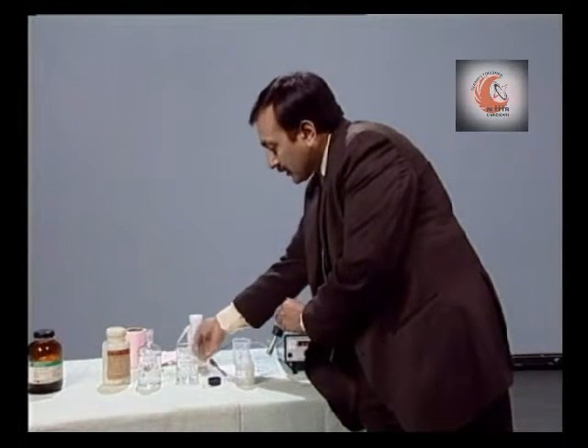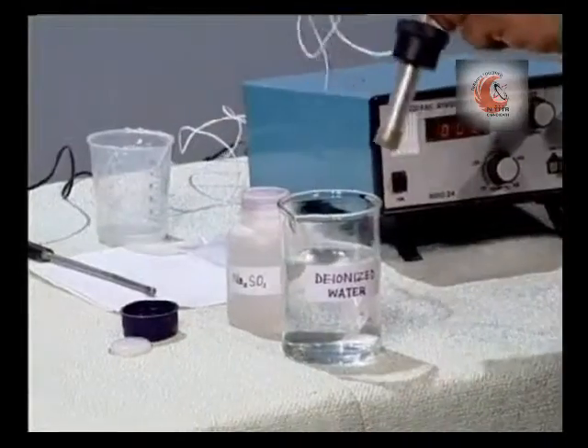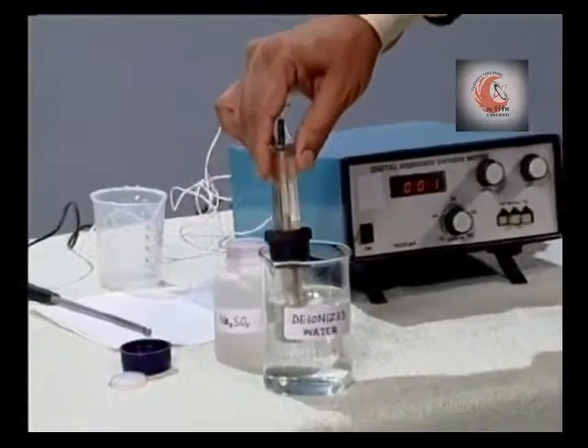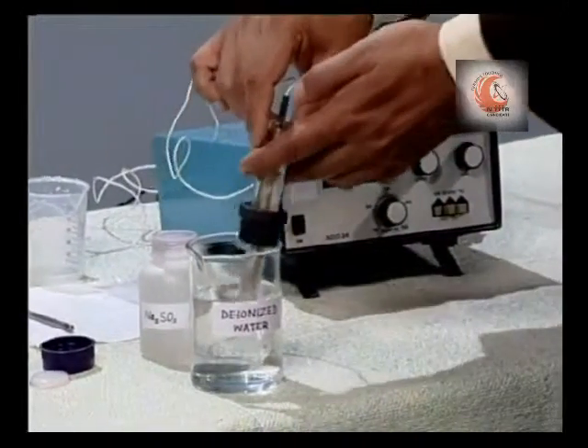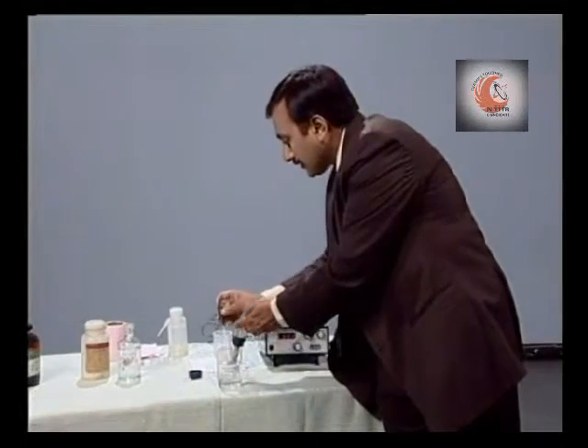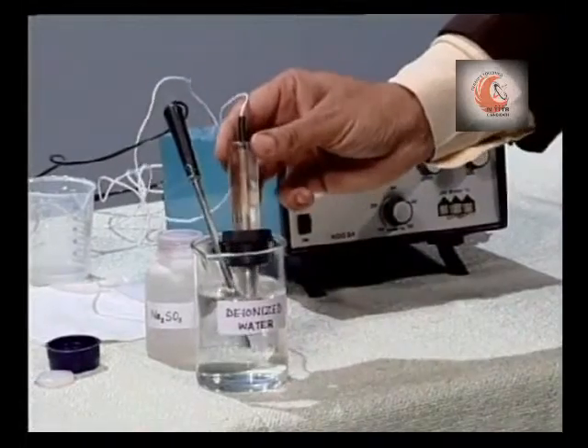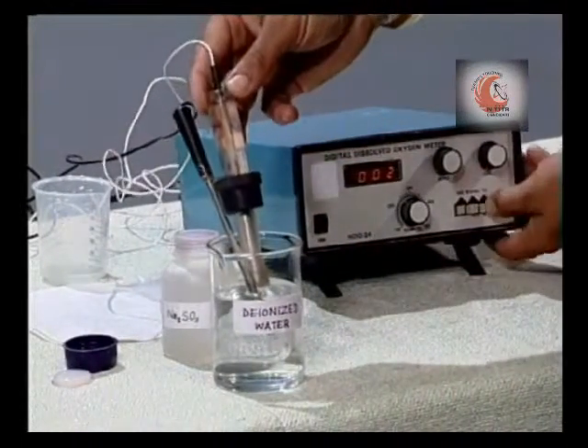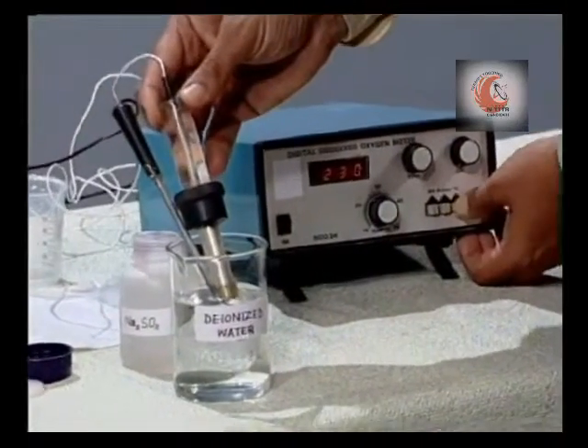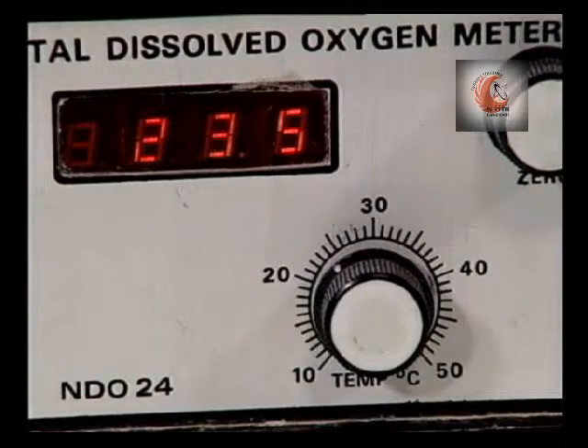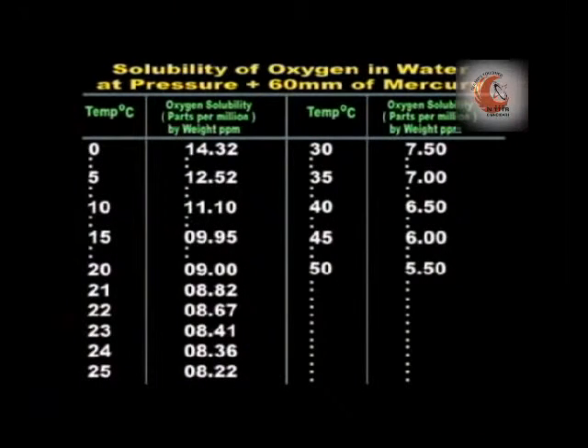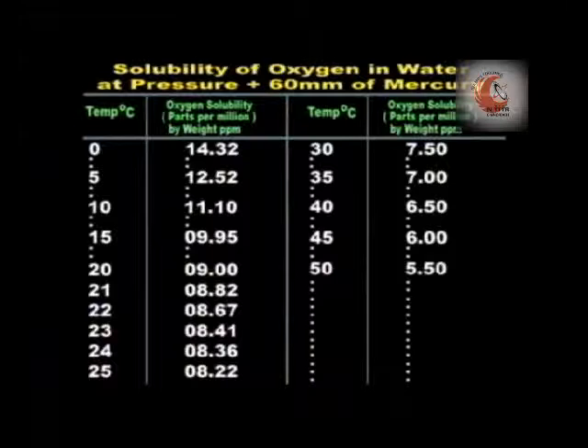Now, take deionized water. The temperature of deionized water is 23.5. The deionized water has a standard amount of oxygen dissolved in it. This depends on the temperature. Corresponding to a temperature of 23.5 degrees centigrade, the DO value is 8.38.